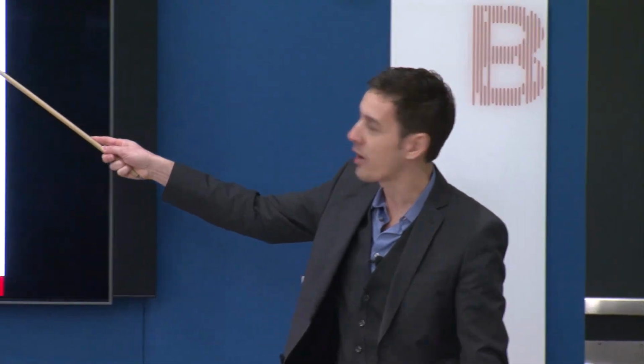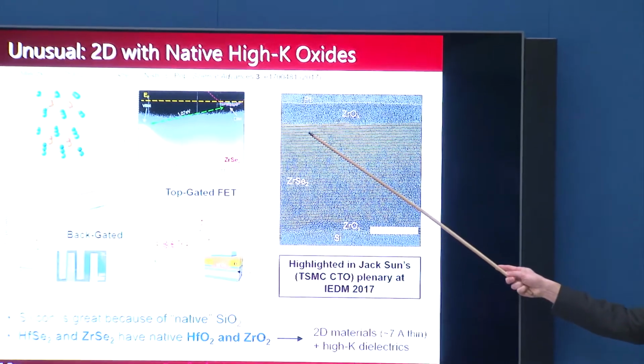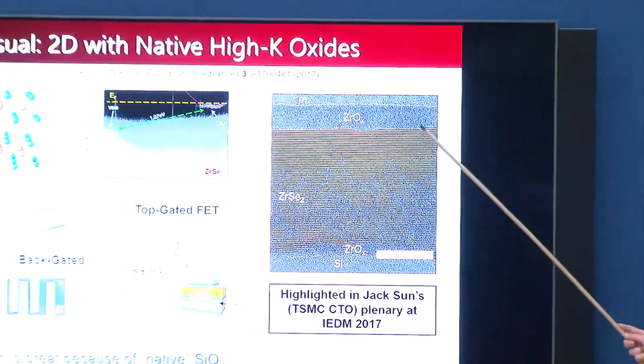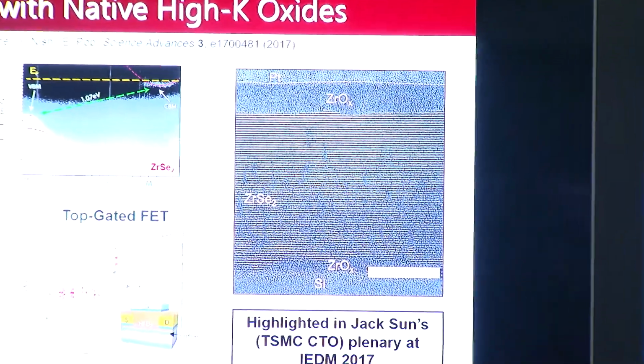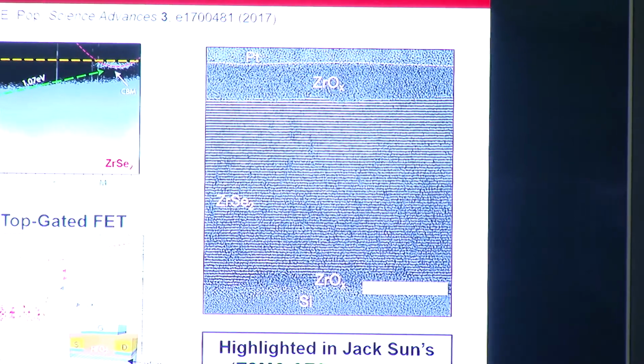I'm trying to remember, it is possible that we had some improvement with a native oxide, but I wouldn't necessarily call these mobilities significantly improved. And part of that could be because we don't have very good control of this oxidation process yet. You see there's this zirconium oxide there at part of the layers, and that's where the inversion layer is. So there's probably some significant, not just remote phonon scattering, but even surface roughness scattering there. And this is really not an optimized process.